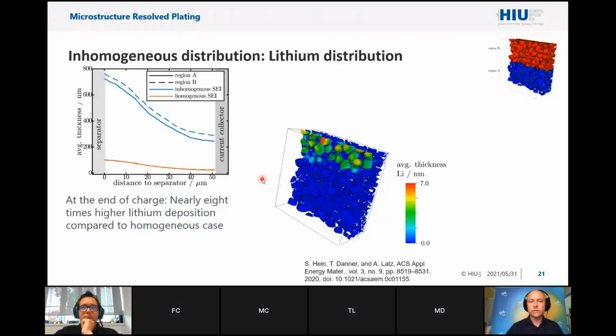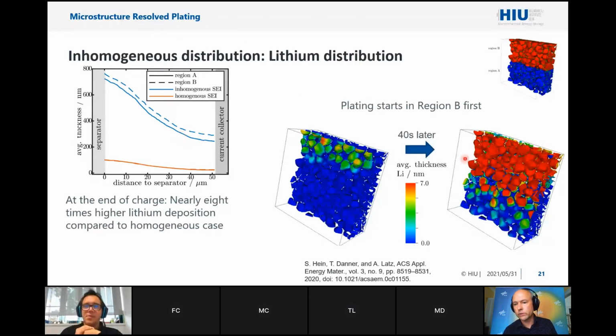So you could argue, well, this is also not surprising due to the larger interfacial resistance, but you also see that in the part which has the same interfacial resistance as the homogeneous one, you get a larger amount of lithium plated, and this is due to a very subtle interplay between overpotentials, interfacial resistance, and redirections of currents. So what we observe in this situation is that we get first plating in the part which has the largest interfacial resistance, or the thicker SEI, and of course there the amount of lithium plated is much thicker than in the part where we have a thinner SEI.